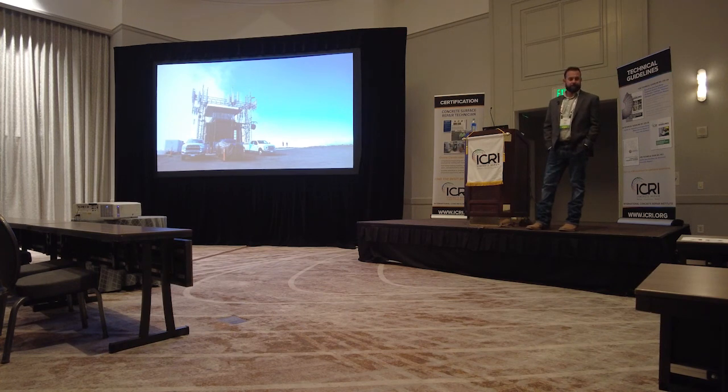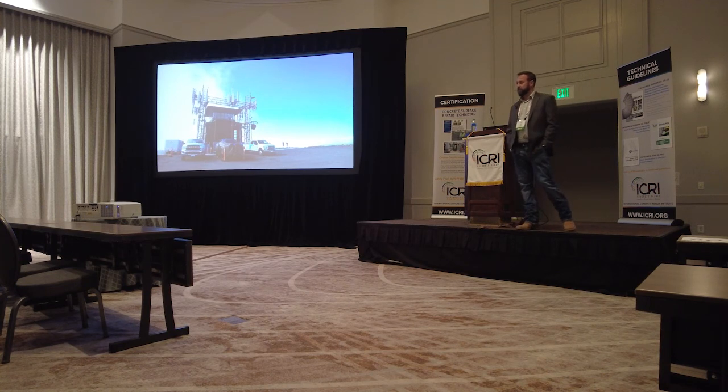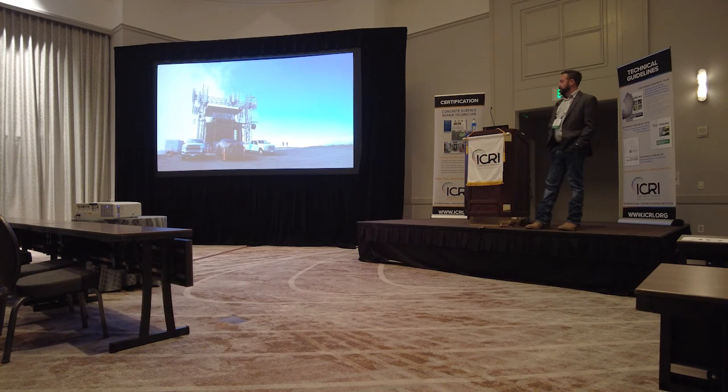Regarding the soft concrete — did you have to pour lower-strength concrete? We ended up at just about 600 PSI — you never want to exactly match, but be at least close to it. What's the anticipated lifespan of the repairs? Realistically, knowing the Park Service and how they operate, they're looking for 40 years out of it. The Park Service ended up forcing Verizon to pay for this. There are several parts of it that would have to be maintained, and in this environment — we had this conversation with them multiple times — the Park Service knows they have to maintain it, though it's difficult for them.